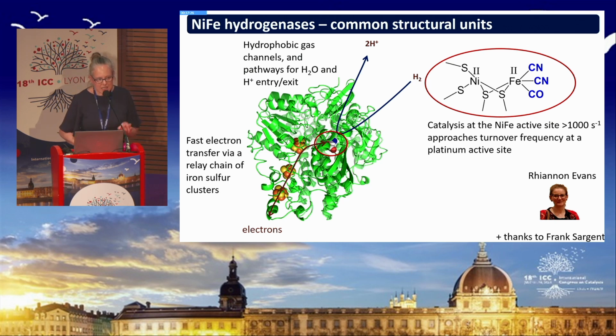As well as having this bimetallic active site, the enzyme has a chain of iron-sulfur clusters that allow electrons to move very rapidly between the buried catalytic site and the surface of the protein. And it also has channels that allow rapid access of hydrogen and protons in and out of the active site. And these enzymes often function as reversible catalysts for hydrogen cycling, able to oxidize hydrogen and reduce protons to make hydrogen.